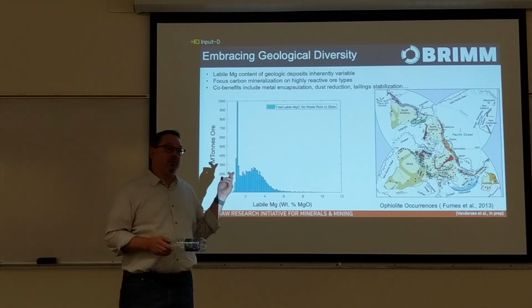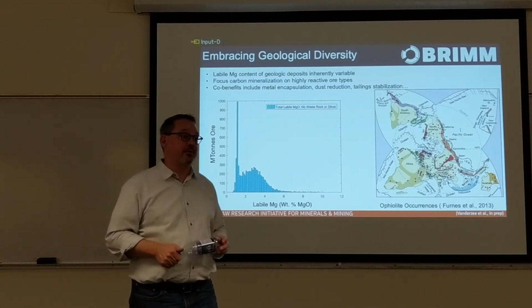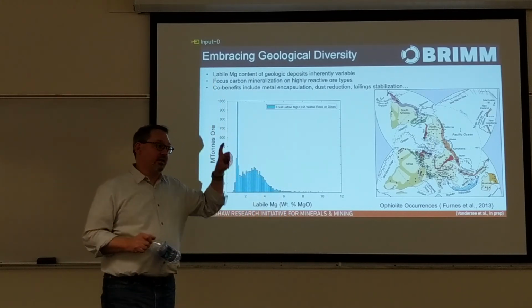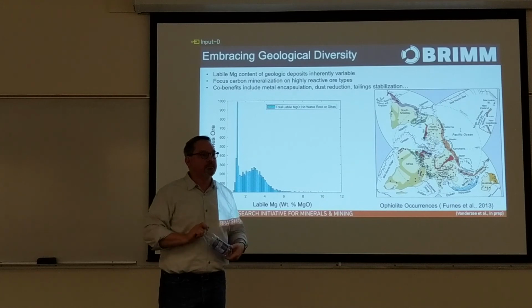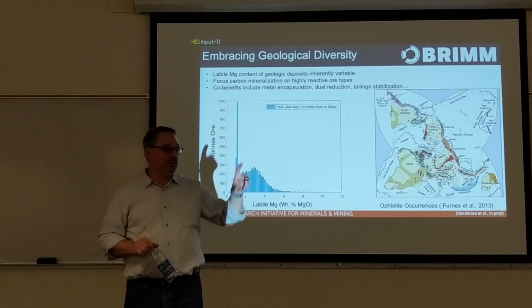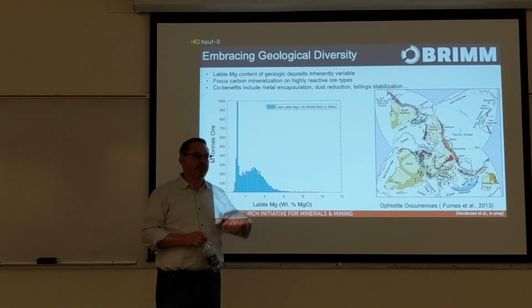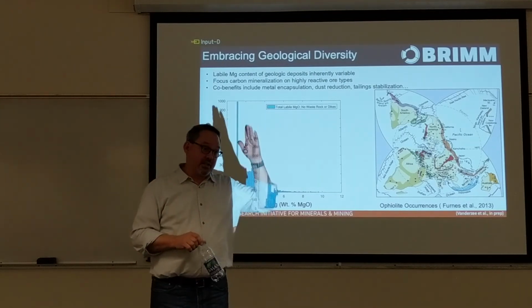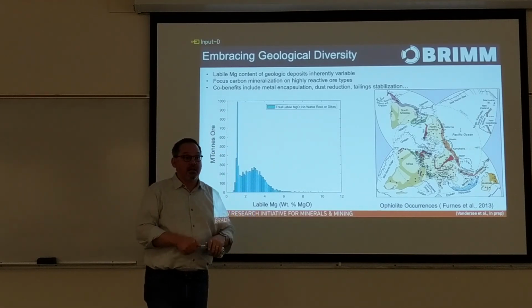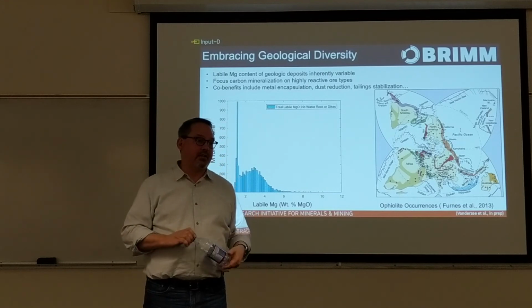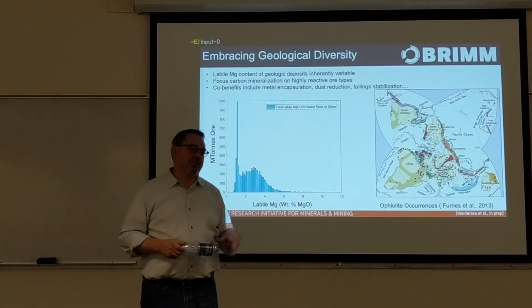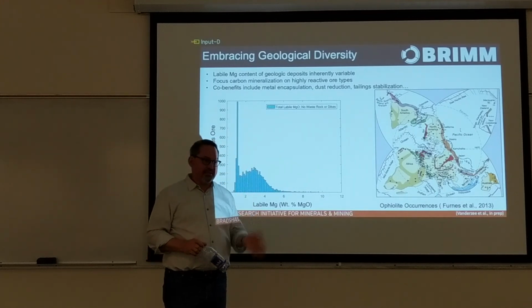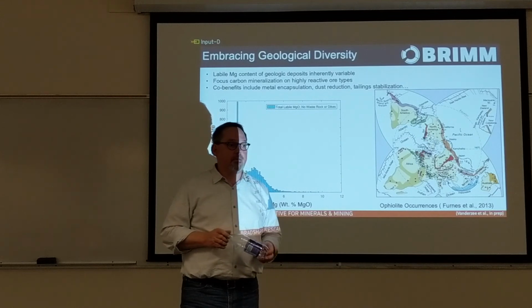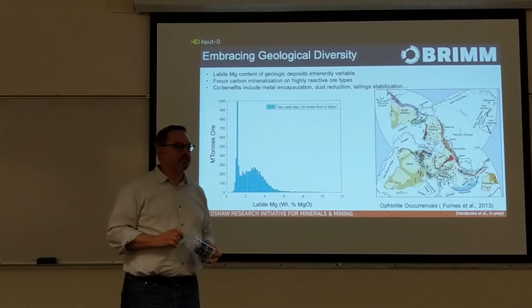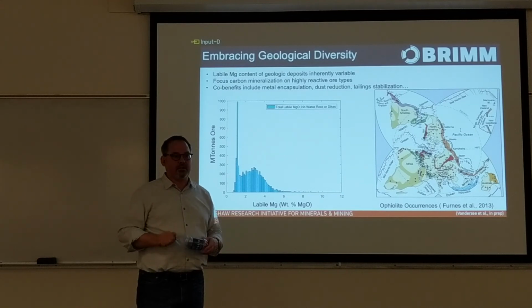Jess Hamilton's work is really just some of the first work that's been done. Ian Power did some leach columns on this scale and put native sulfur on the top, and it was going from pH 0.5 to 9 over this distance, and none of the metals were coming out the bottom. That pH gradient was enough; he was getting magnesium sulfate at the bottom, essentially generating sulfuric acid with sulfur-oxidizing bacteria in that system. So you're leaching magnesium sulfate, but not the other metals. But nobody's done large-scale tests.